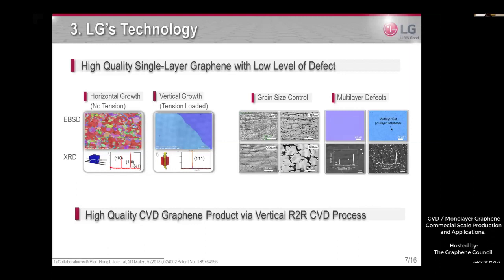The control of crystal orientation of a copper substrate is a key factor for high quality graphene growth. The vertical geometry could adjust the copper crystal orientation for optimized graphene growth. Graphene growth under tension using the vertical CVD system shows larger grain size and fewer defects. We control the grain size, as shown in the SEM image, from 5 square micrometers to 200 square micrometers. And we also minimize defects such as the multi-layer dots. In this image, it is very clean. There are only a few multi-layer dots, but in the normal case, there are lots of multi-layer dots in the CVD graphene sample.